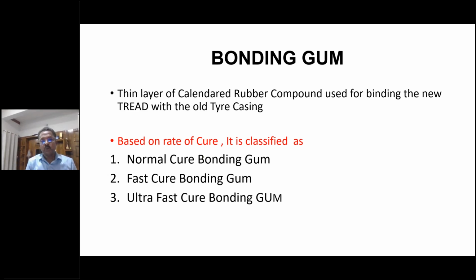Bonding. See, bonding is a very, very important material for retreading. For example, we use a 12 kg tread. The bonding is about 1 kg, 1.2 kg. The main purpose of bonding is to bond the new tread with the old casing. It's a very critical material in tire retread. Based on rate of cure, it is classified into 3 different categories: normal curing bonding, fast cure bonding, ultra fast curing bonding. So based on cure rate, we can reduce the cure time in the electric chamber or cure time of retreading. At the same time, as the cure rate increases, the shelf life reduces.